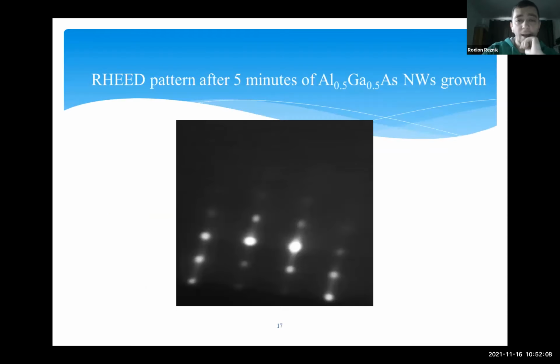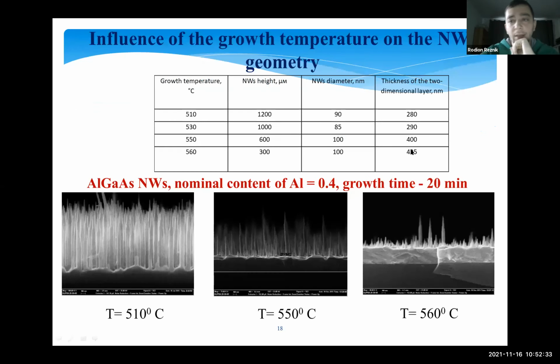So first of all, we start with growth of aluminium gallium arsenide nanowires on silicon substrate for the first time, using gold droplets. So this is a typical SEM picture after some minutes of growth. And first of all, we try to find the optimal growth parameters for aluminium gallium arsenide nanowire growth. Here you can see different growth temperatures for nanowires from 510 to 560.